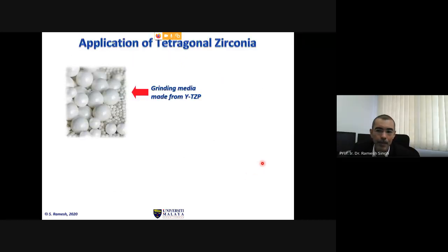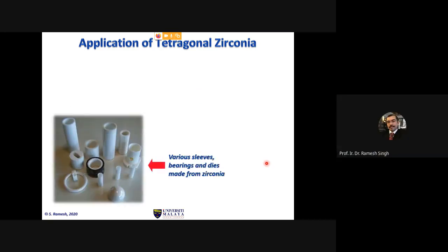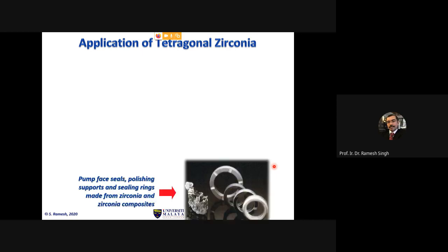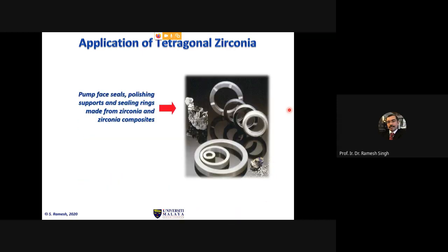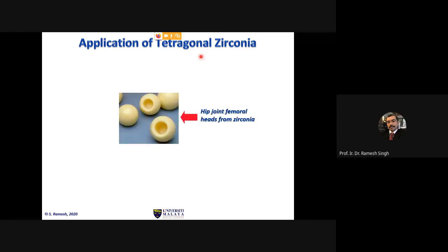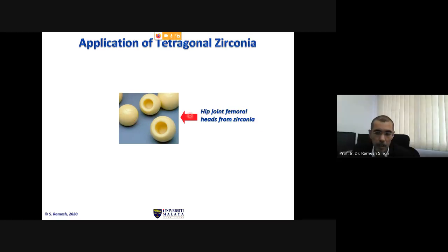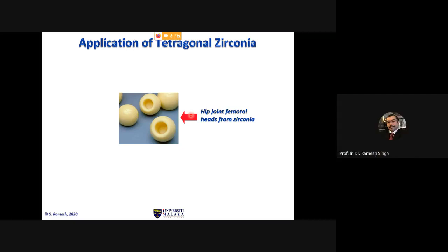Right, so many applications for tetragonal zirconia. We can use it for grinding media, sleeve, valve, dies, as pump face seals, polishing support, seal rings. I mentioned just now about the total hip replacement. We can make the femoral hip out of ceramic. In research, it has been shown that when we use ceramic, the friction is very low, and therefore patients having the implant may not need to go through surgery again when the implant is loosened because of friction and so on. So you can prolong the lifespan of the implant when you actually use it in the body, okay, because you keep the friction low.